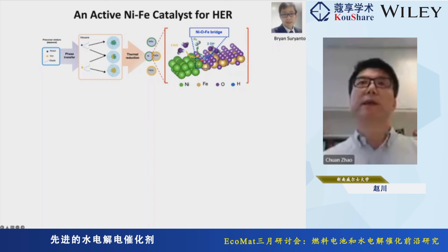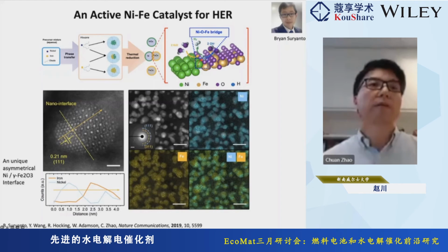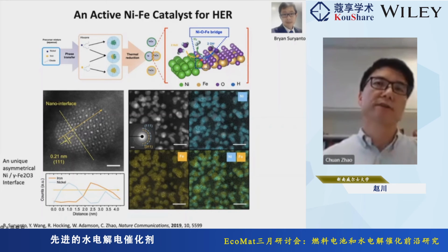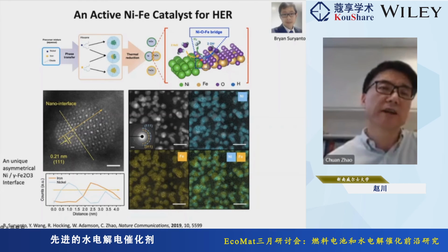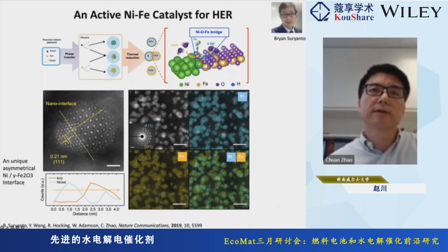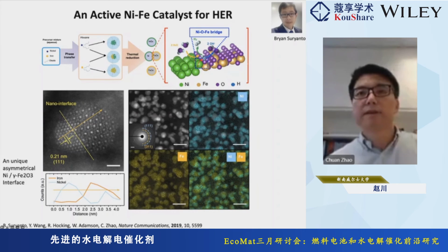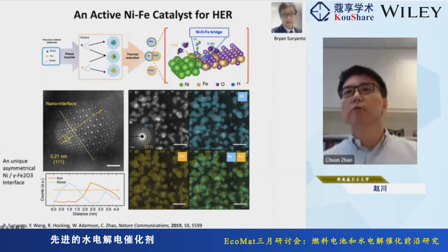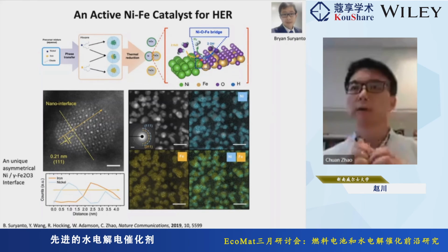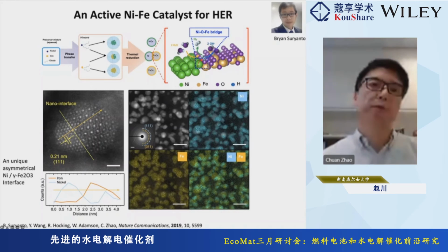So what we have here is making a nanoparticle using a micelle-based synthesis, and we can have a catalyst which has a distinctly different phase of crystal structure as well as conductivity. We actually end up with a catalyst with a nickel metal and also an iron oxide phase. From the EDAX mapping, we can form numerous stable nano interfaces, where the HER is supposed to happen.